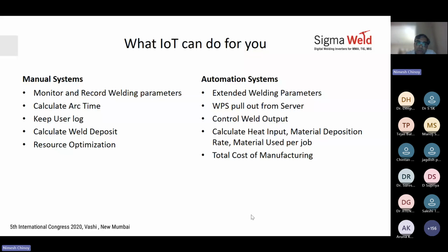Once you have this data, you can also evaluate or calculate the weld deposit. If you know what wire size was being used, for example, in MIG welding, if you're doing 1.2 solid wire, stainless steel or carbon steel, you have a particular density. You welded it at this speed for 10 minutes. So you fed that material for 10 minutes at this particular speed. This is the amount of wire you consumed. You know the mass, you can calculate and figure out the weld deposit that you had. Similarly, resource optimization. That means if I have 10 machines, but these 3 machines were not being used at all throughout the day, my arcing time is only 5%, then I can use these resources for other things.